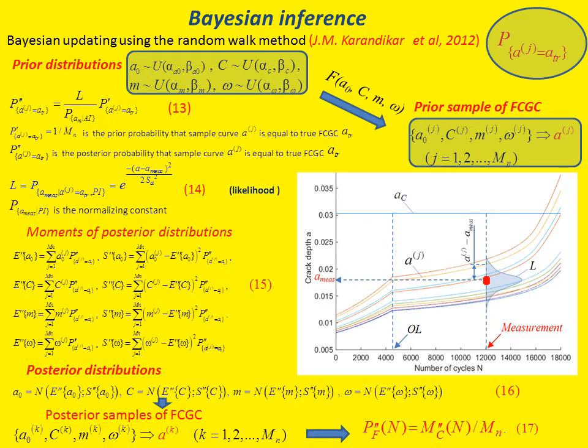It should be noted that the likelihood function defined in equation 14 does not completely reject curves which differ significantly from the experimental result. It simply yields a small weight value for these curves. As soon as we get the posterior probabilities of crack curves, we can determine the moments of the underlying distributions of uncertain parameters. Here they are defined by equation 15. As we managed to reduce the level of uncertainty in the model parameters, we can further assume that the posterior distributions of uncertain parameters are Gaussian.